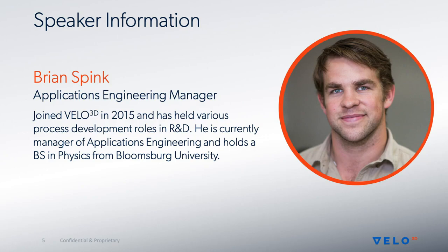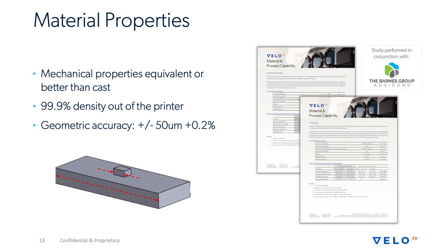Right, real quick, high level on material properties. The material comes out pretty much on par with other laser powder bed systems that I would say are running very well. The mechanical properties are very similar or better than as-cast material. It comes out fully dense. And the geometric accuracy, the rough rule we use, is it's accurate within plus or minus 50 microns, or that's 0.002 roughly, plus 0.2%.